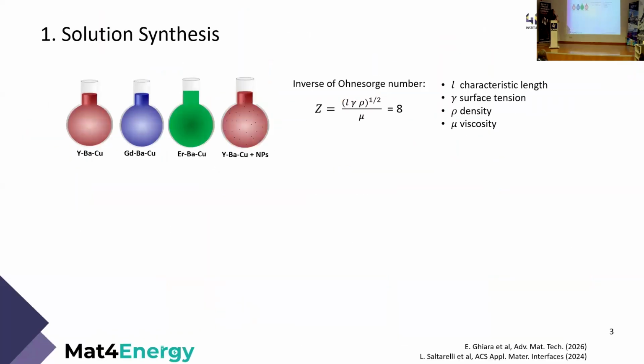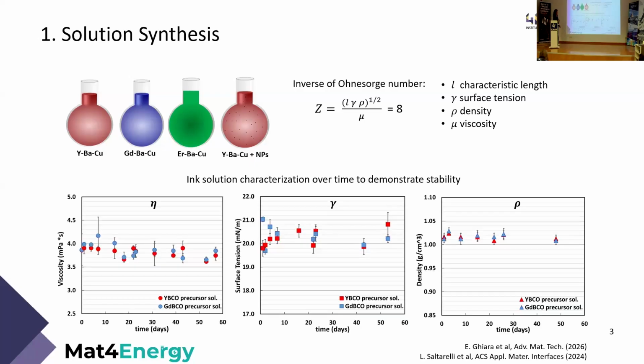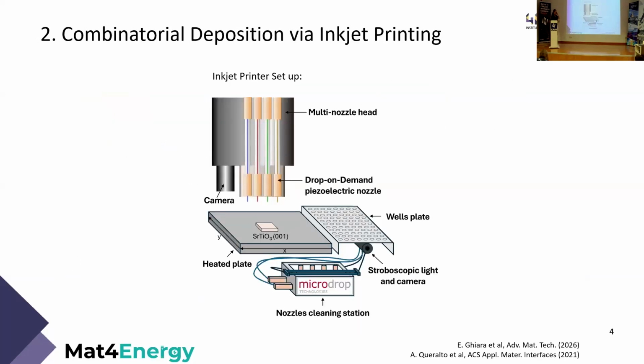So the precursor solutions are synthesized here in-house, and they may contain different types of rare earths such as yttrium, gadolinium, or erbium. And additionally, they may contain nanoparticles. An ejectability study was conducted in the beginning of my PhD in order to be sure that we can use this solution as ink. And this is mainly given by the rheological properties, so viscosity, surface tension, and density. We can see here that this ink remains stable for at least 2 months, so it's good from a stability point of view.